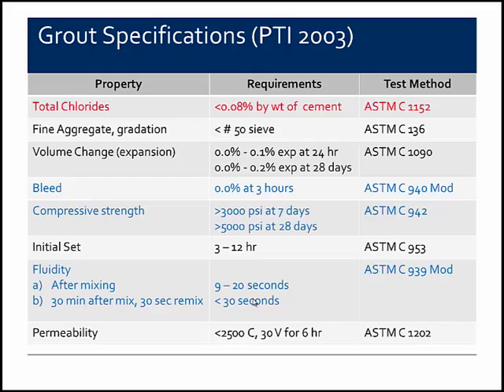The three tests in black, the fine aggregate, the volume change, initial set and permeability, are all run, once again, during trial batching. They may be run by an owner to verify a lot of grout or a shipment of grout meets the specifications, but it's not normally a test that's run in the field every day or even on every project. The blue tests, the bleed, the compressive strength, and fluidity, at that time were run in the field generally every day when grouting operations were conducted.